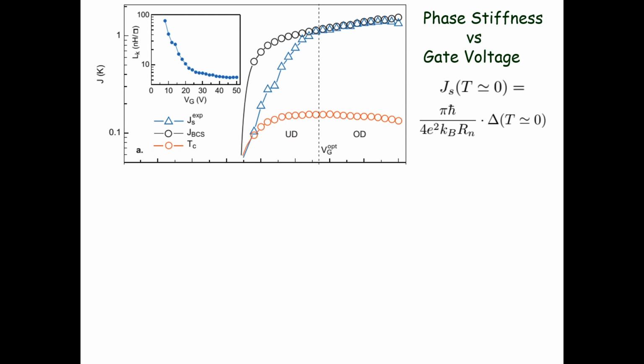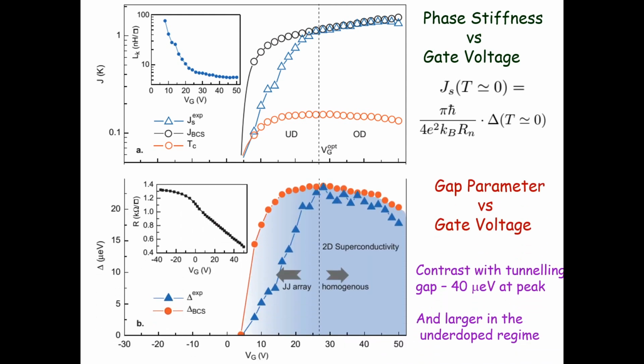All right, I can go a step further and calculate the gap parameter. So what do I do to calculate the gap parameter? So this is my experimental gap parameter. I'm using this formula: phase stiffness is related to the gap parameter. So this is the gap parameter calculated using the BCS theory, gap is equal to 3.5 kB Tc. This is the behavior of the gap. On the other hand, if I calculate the gap using this formula for the phase stiffness, the gap parameter comes out like this. So there is a clear difference here. Below here they merge together.